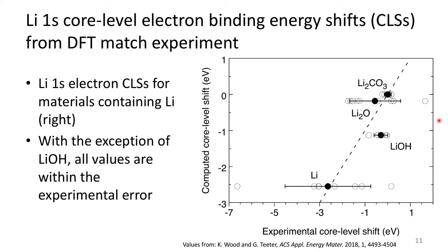One way to assess the electronic structure is to look at the core level electron binding energies for lithium 1s electrons in different binding environments, which for our purposes is lithium metal and Li2O. This is equivalent to determining energies from XPS. This technique is not very common in the computational literature, so I wanted to benchmark the core level shifts, which are relative electron binding energies. Here I computed the binding energies relative to lithium carbonate, since lithium carbonate has the least amount of variation in the data set of experimental core level shifts from the XPS that I used.